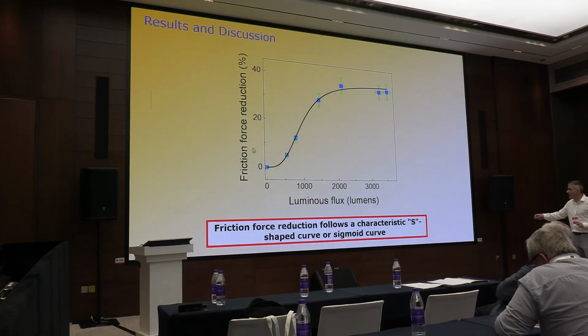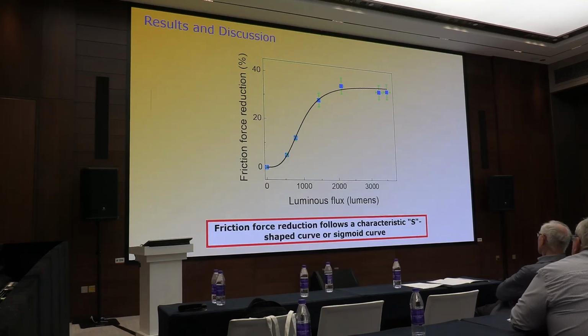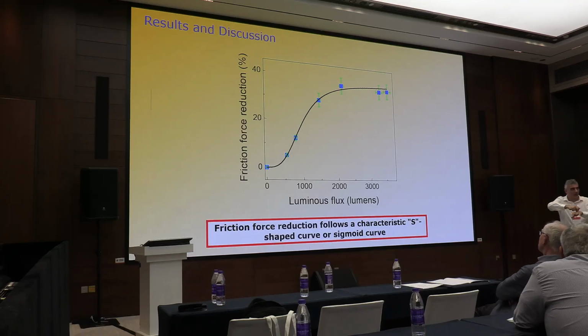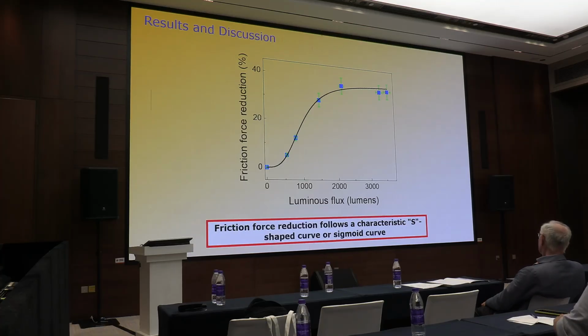This S shape or sigmoidal curve is very common for photocatalysis of titanium dioxide with organic molecules. It's very common to see this type of curve in aqueous solution photocatalysis of different organic molecules on titanium particles or nanoparticles of titanium dioxide. So this is very interesting because there is a correlation, but it's a different system: that is aqueous solution, this is solid. This is a dry sliding on the titanium dioxide, solid on solid. But the correlation is similar to the aqueous system of titanium dioxide and photocatalysis.